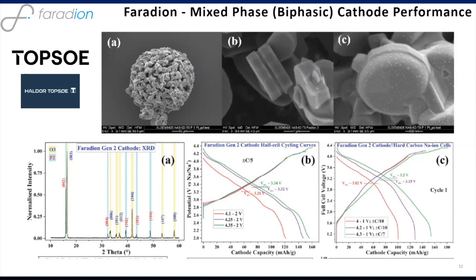In our current design, one of the typical materials we used is shown here. Under micrographs, what you see is the agglomerates are made from smaller primary particle sizes. The agglomerates are somewhere between 10 and 20 microns in diameter. These end up giving you pretty good tap density. If you look at it under much higher magnification, you get these intergrowth materials. And this allows you to get the synergistic positive effects of the O3 and the P2.